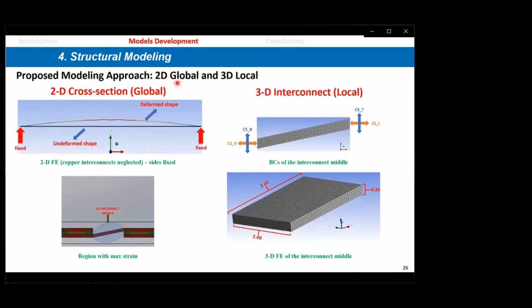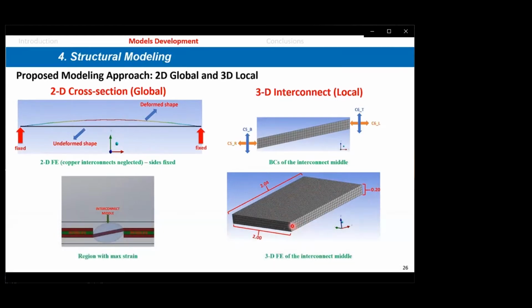So based on one string, two-dimensional simulations, we define the maximum deflection, which leads to maximum stresses, and it happens to be in the central part of the copper ribbon, as you can see in this case here, which is not surprising. Now we take whatever boundary conditions in terms of temperature and stresses and so on apply to this, and we use a three-dimensional finite element, as you can see from this 3D mesh, to analyze the fatigue behavior of the interconnect.